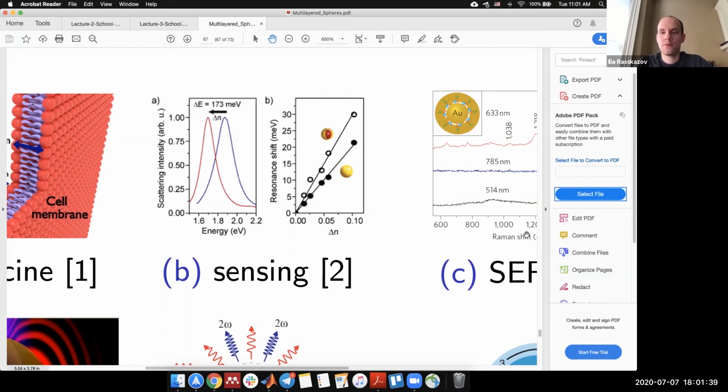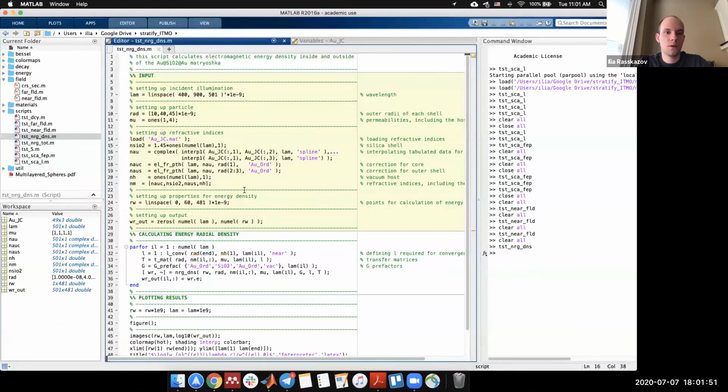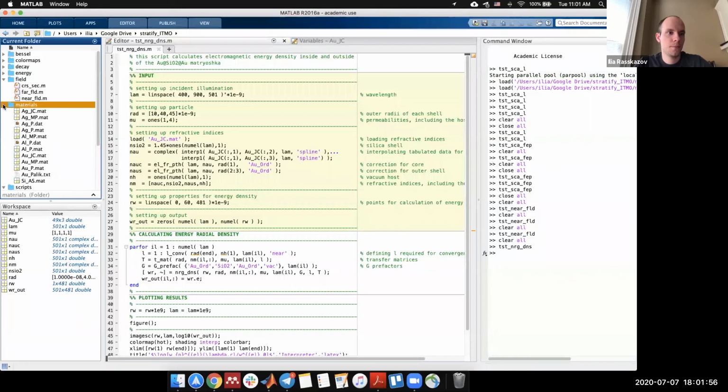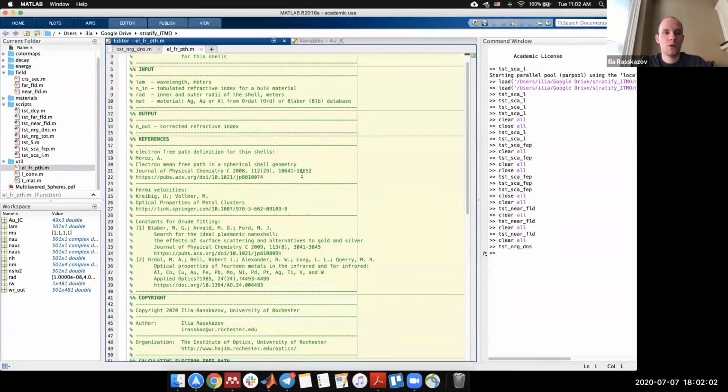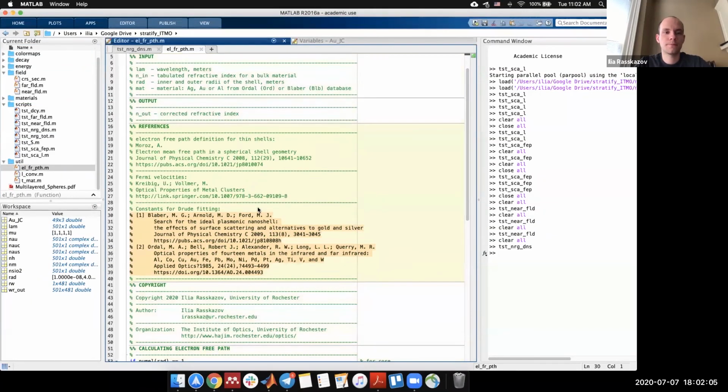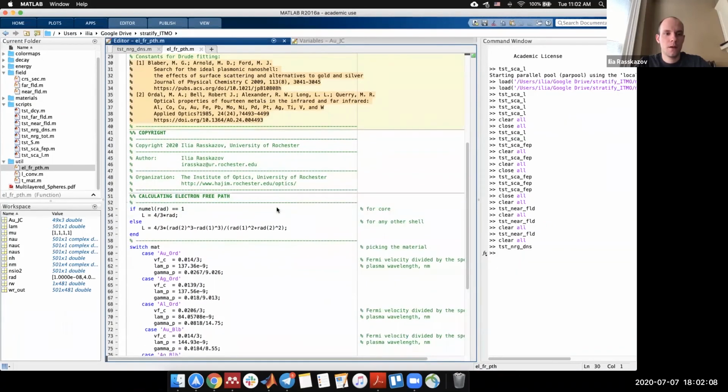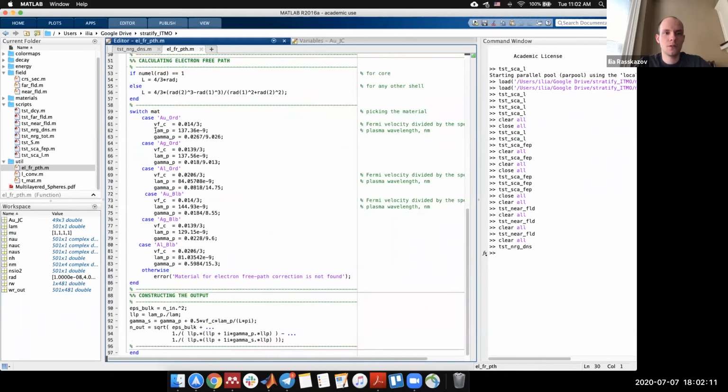Yeah, Raghav, I have discussed that the gold permittivity is taken from Johnson and Christy data. Yes, the plasma frequency of the gold can be found, very straightforwardly, from these two papers. And here for gold, I'm using not frequency, but the wavelength. Doesn't matter, you can convert it to frequency. For gold from different references, it's either 137 or 144.